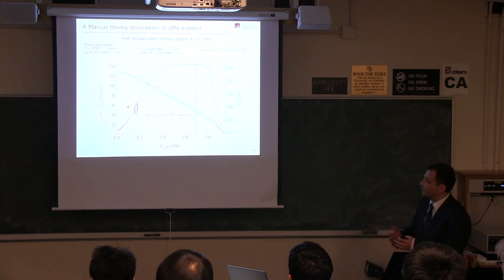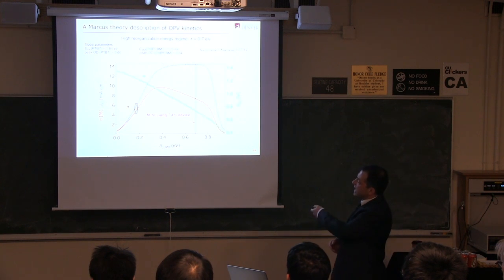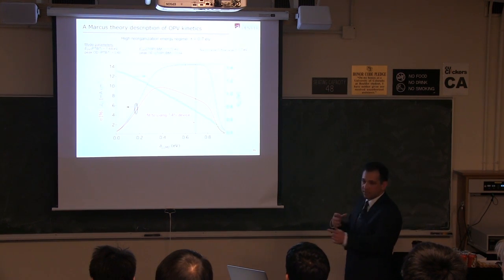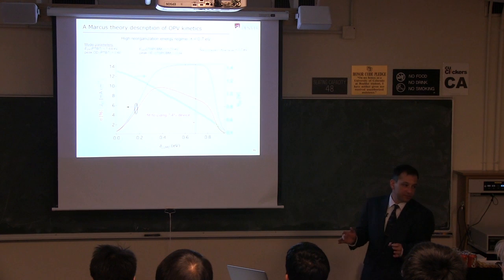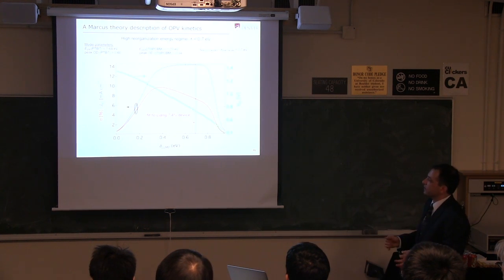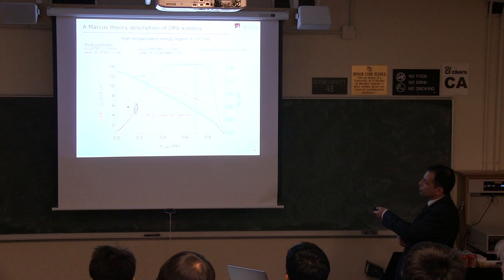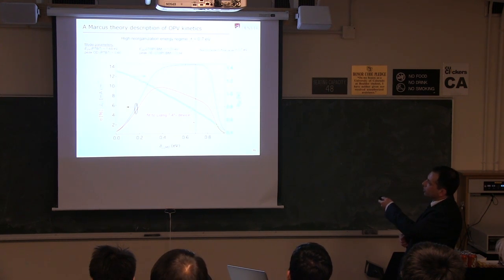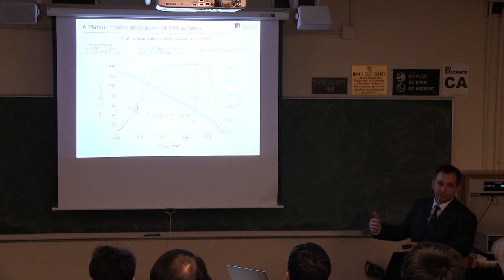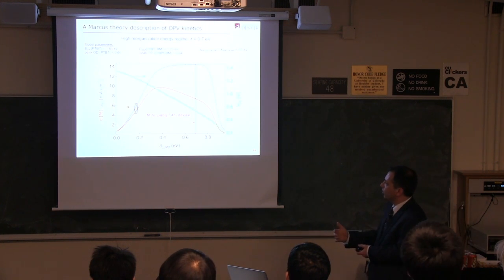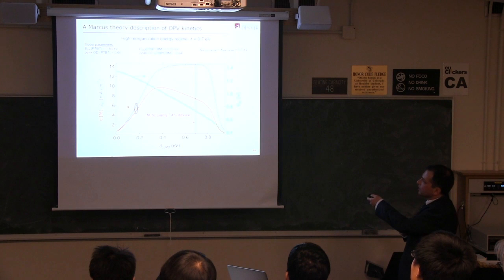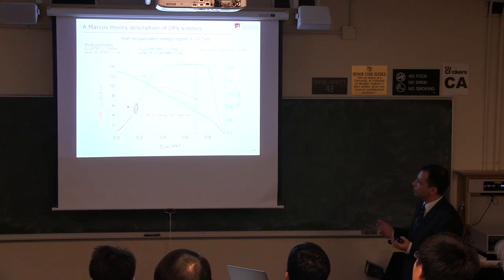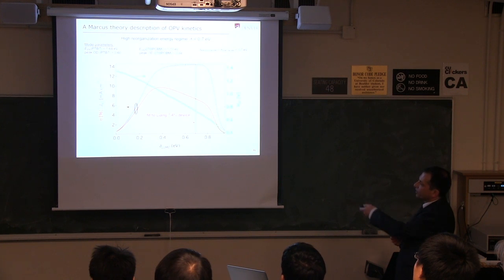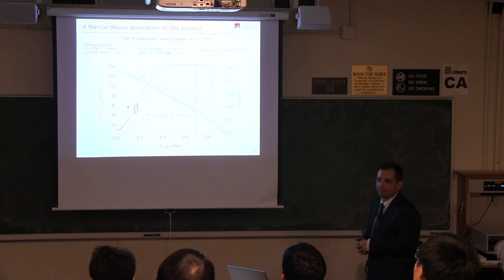Now we're going to do a hypothetical circumstance of can we change delta LUMO in a systematic way without changing anything else. If we can do that, then things get very optimistic. We can reduce the band offset, increasing the voltage of the device, and the current, which is basically saturated because you're absorbing all the photons and extracting all the carriers. You're not losing any current because the kinetics still is working out. And so if you keep doing that at a band offset of about 0.4, you get to 10% efficiency, right? Hypothetical.